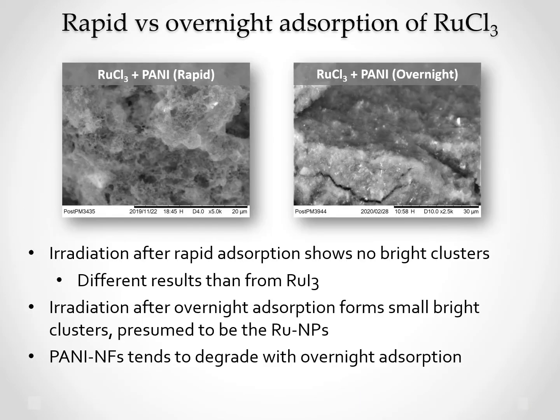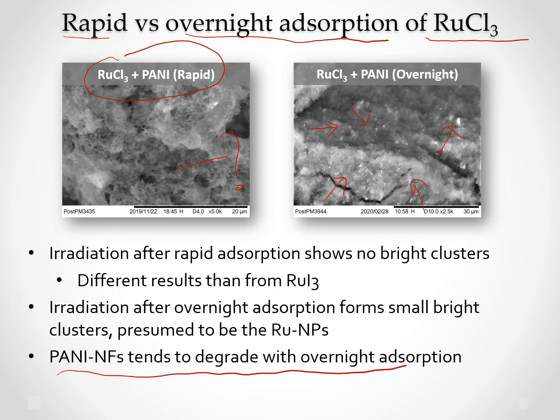Next is the comparison between rapid and overnight adsorption of ruthenium chloride. In rapid adsorption, there are no clusters; however, in overnight adsorption, we notice several clusters. The PANI nanofibers tend to degrade with overnight adsorptions.